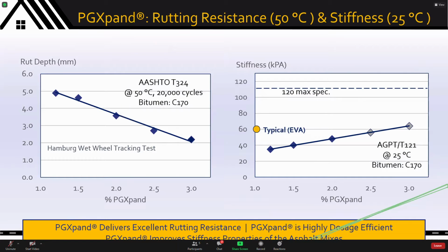This data comes to us courtesy of Australian customers. Plotted here is a very similar curve, Hamburg wet wheel tracking, in this case done wet at 50 degrees C. You can see as a function of dosage of PGXpand loading, the mix shows increasing rutting resistance.